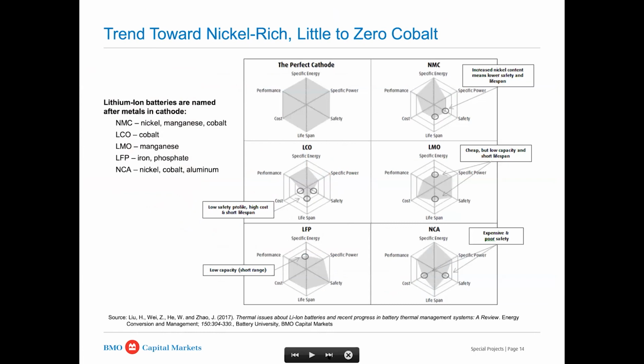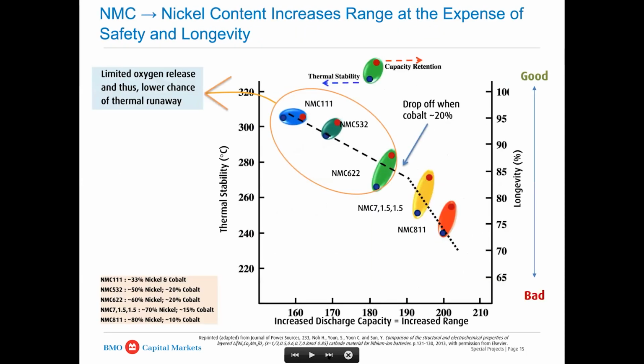So the perfect cathode doesn't exist. I use this slide all the time. It's very useful, and it lets us take a look at all of the parameters. The key ones: NCA is what Tesla uses, and that's nickel, cobalt, aluminum. The rest, outside of China and in the higher end vehicles, use NMC, high nickel. They're trying to push nickel higher in both formulations, and we're finding that there's actually a convergence between the two. People are actually doping, replacing cobalt in the NMC formulation with aluminum, because they interact in the same way. So just to give you what the issue is with nickel. And the last thing I just wanted to talk about was that nickel's the star.